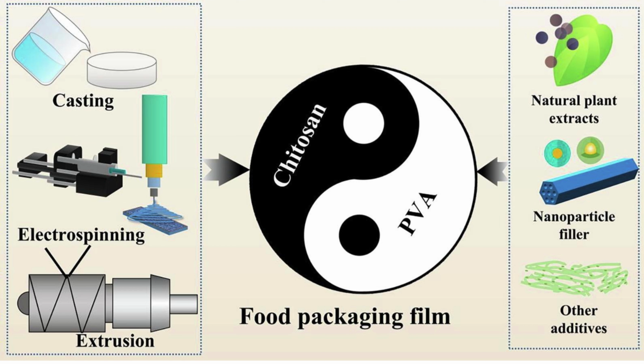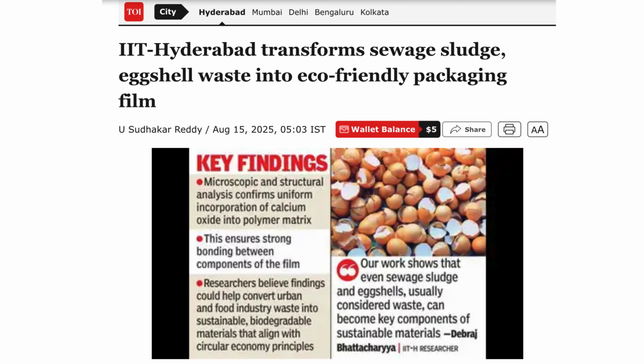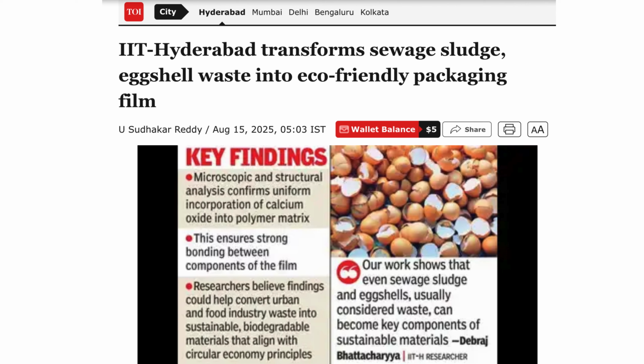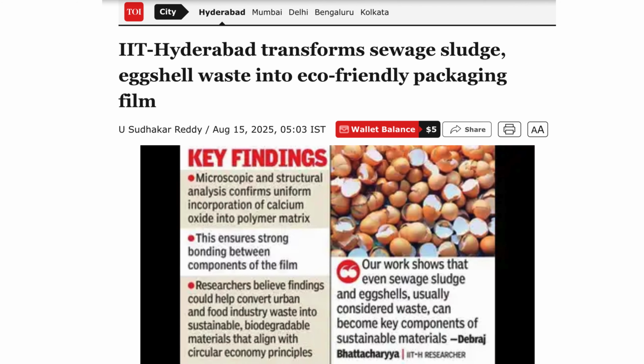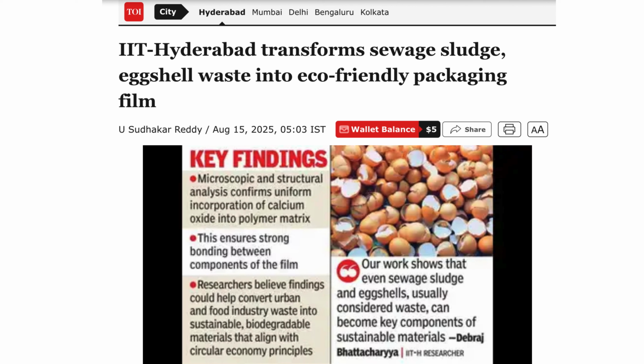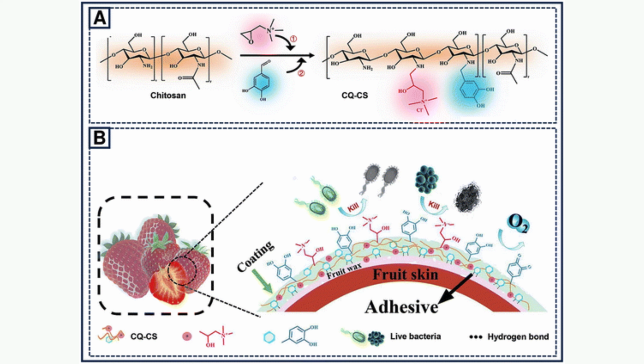Case study, 2025. IIT Hyderabad reported a nanocomposite film from sewage sludge EPS plus chitosan plus calcium oxide nanoparticles, eggshell-derived. Even though it's not for food contact, it hits circular economy marks and improves tensile strength, elongation, and water barrier. Muscle-inspired barrier/adhesive layers. Catechol/tannic acid chemistry, grafted onto chitosan, improves wet adhesion and enables antimicrobial coatings for food preservation.